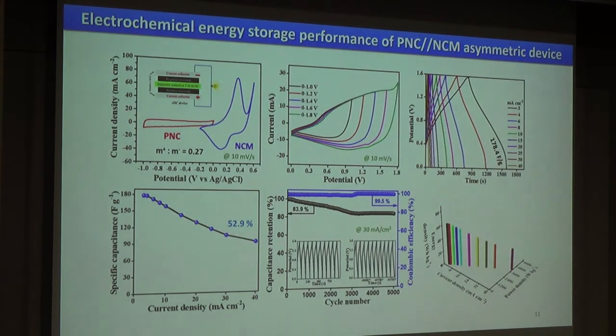Now the asymmetric device fabrication was schematically shown here, and their cyclic voltammogram of the porous nitrogen carbon and NCM was compared here. To decide the potential window of this asymmetric device, we carried out cyclic voltammograms at different potential windows, and we observed that after 1.6 the water dissociation starts, which indicates that 0 to 1.6 is the optimal potential